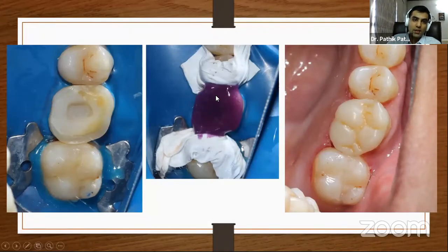And as we discussed the cementation protocol, etching was done after Teflon isolation of the surrounding adjacent teeth. And I applied the dual cure Futurabond DC. If you have Futurabond DC, they don't insist that you need to etch the tooth surface, but for my own better result, because currently I don't use a sandblaster or air abrasion instrument in the oral cavity, at least I need some basic etching of the enamel. And then using Futurabond DC, not curing it, and using Bifix QM to lute this endocrown, and then tack curing first, removing the extra, and then curing it properly under glycerin.